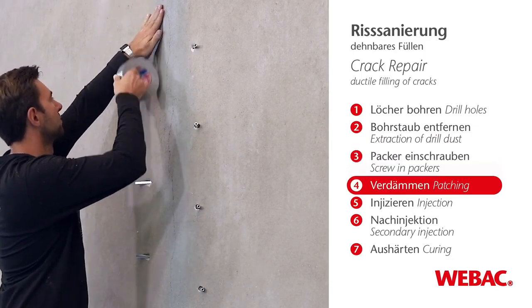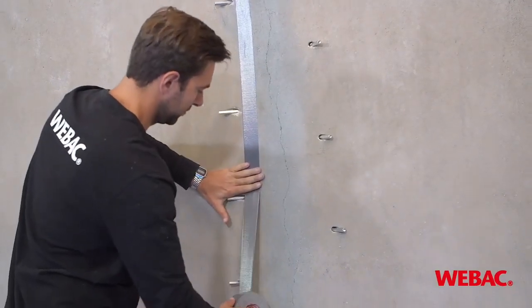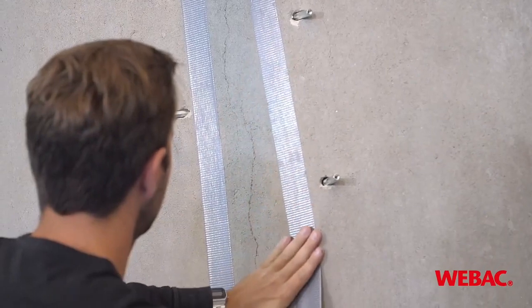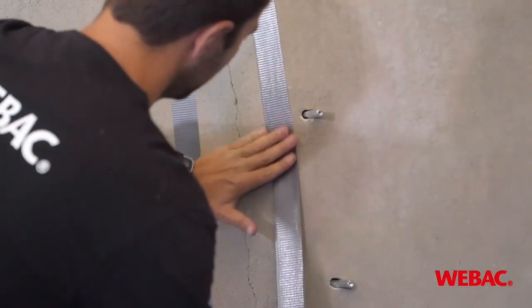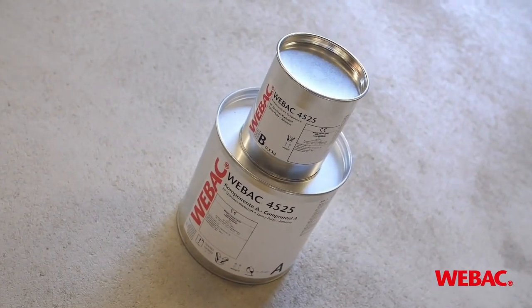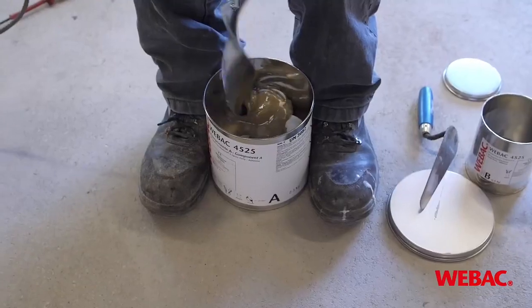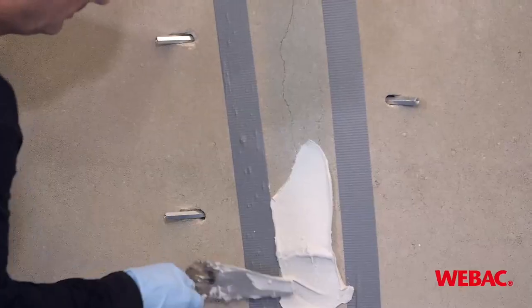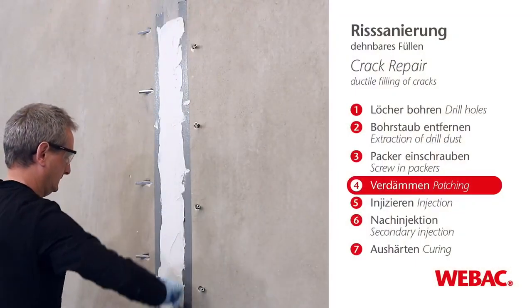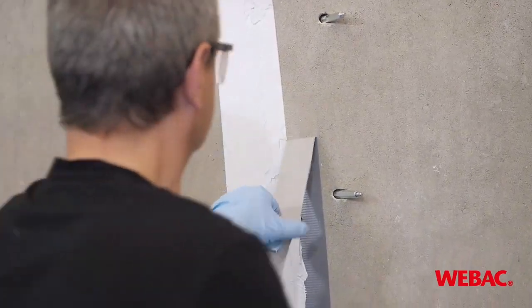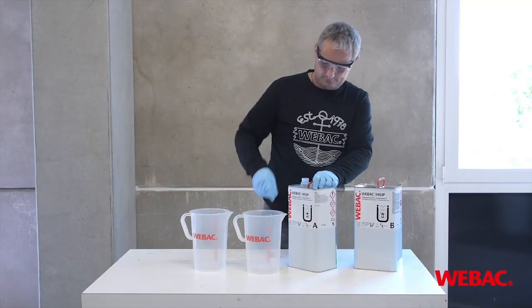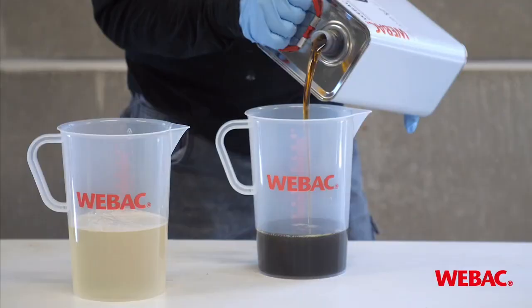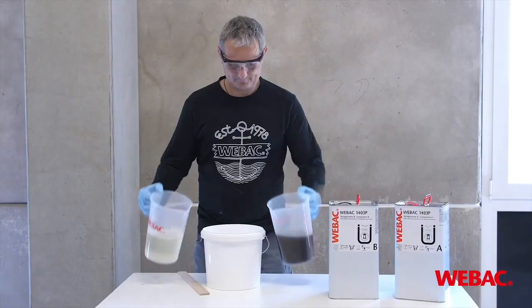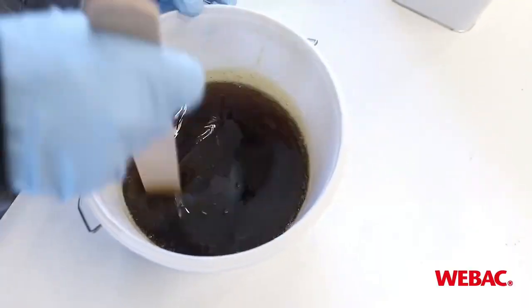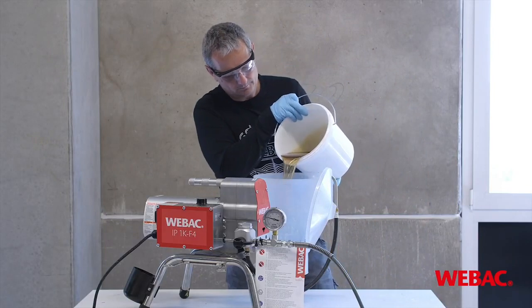Afterwards, you are installing the packers and patch the crack, simply to prevent that material which you are injecting in the packer is coming out immediately to the inside of the building. You would like to push the material, we have seen it in the earlier graphics, to the outside of the building. Very important, at the top of the crack, leave a venting opening. In this case, we are using polyurethane injection resin for the ductile filling of the crack, so it can take some movements.